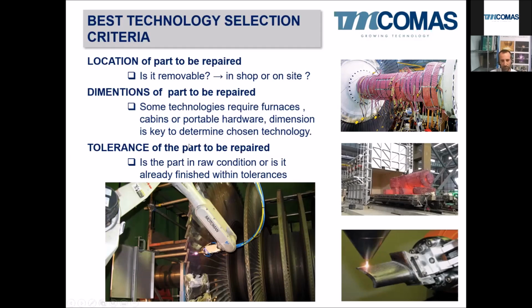Also, the tolerance of the part to be repaired. It's not the same if the part is in raw condition or if the part is already finished with tolerances. If the part is in raw condition, like this one, it means that it has no tolerances, or the tolerances are very big. So we can use very aggressive heat treatments if needed. On the other hand, if the part is already finished, like these turbine blades in this multi-stage turbine, it's clear that the dimensions are finished. So we are going to need different techniques that are not going to cause a deformation or a big alteration in shape, because we can spoil the parts.